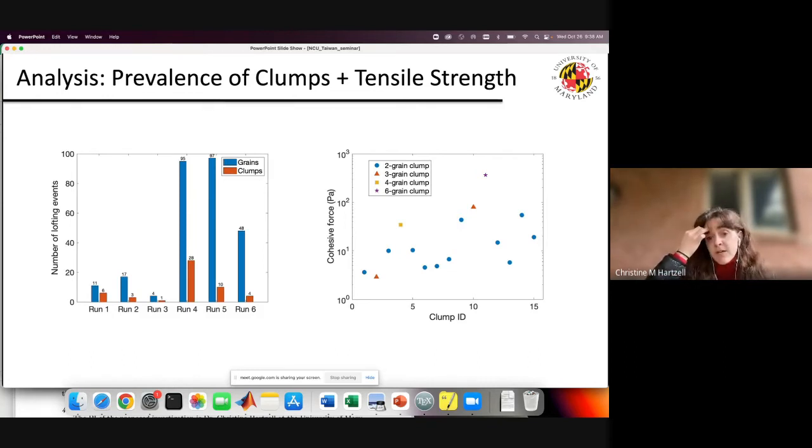So we can solve for that cohesive force, then we can divide it by a surface area, and that gives us really a tensile strength, not a cohesive force here, for particles and for the regolith simulant that we're using. So the tensile strengths that we're getting are between about 10 and 100 pascals, which is pretty reasonable considering behaviors of powders in vacuum.